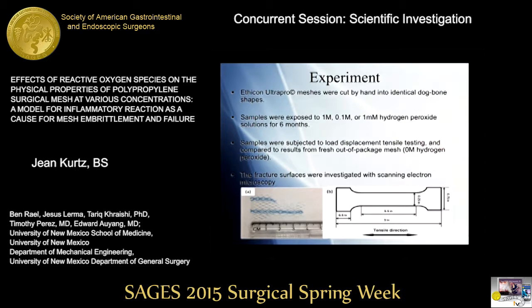The samples were subjected to load displacement tensile testing after 6 months, and they were compared to fresh, out of the package meshes of the same brand in the same dog bone shape. We call those 0 molar because they've never been exposed to hydrogen peroxide.